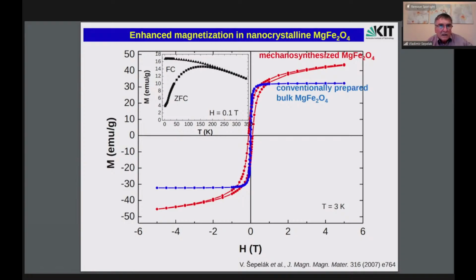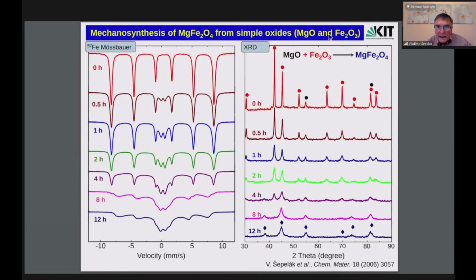the bulk effect on the magnetism of nanomaterials, and it is done for mechanosynthesized magnesium ferrite. You see that we have enhancement of magnetization in the case of mechanosynthesized magnesium ferrite in comparison to conventionally prepared bulk magnesium ferrite. And here it is demonstrated that the mechanosynthesis of the magnesium ferrite proceeds directly, there are no intermediate phases. We have a reaction time of 12 hours, and Mössbauer spectroscopy clearly indicates a disappearance of iron oxide, hematite. You see no traces of this compound in the 12 hours milled material, in mechanosynthesized magnesium ferrite.